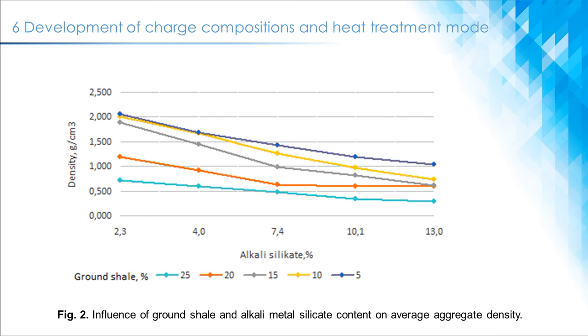Adding a part of crushed shale to the slurry made it possible to obtain an aggregate with a lower average density than in the previous case. This dependence is shown in Fig. 2. A decrease in filler granules' average density with the same fraction of the crushed charge occurs due to an increase in the liquid phase amount. This is because liquid glass forms more melting eutectics with shale minerals and more intense gas evolution occurs.